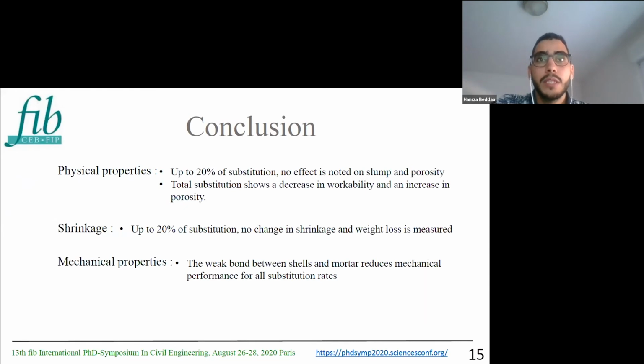So to conclude, this study focuses on the effect of shells of Corbicula type, which are omnipresent in the sediments of Île-de-France region. The substitution of 20% by volume of coarse aggregates by shells showed no effects on slump and porosity, shrinkage, and weight loss. However, a total substitution makes the effects of the shape and the high paste demand of shells more pronounced by decreasing slump and increasing porosity.